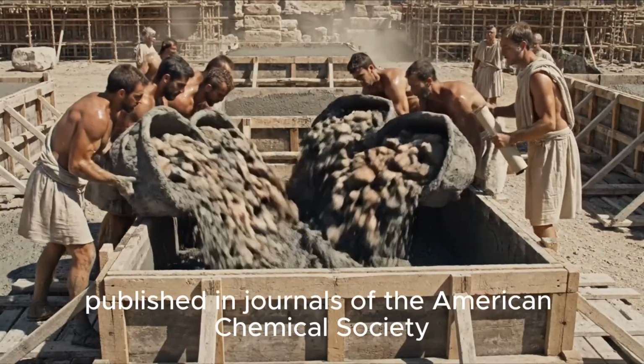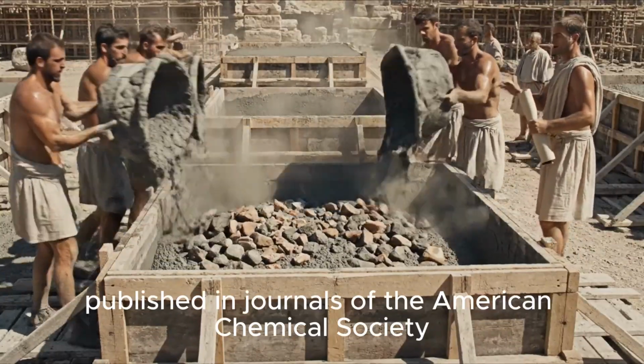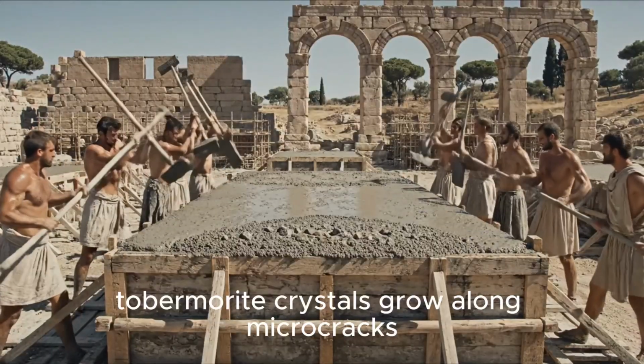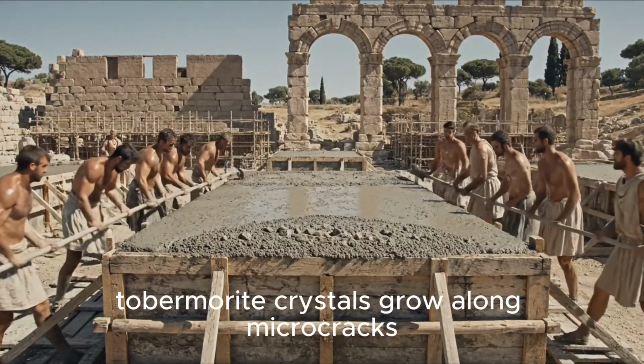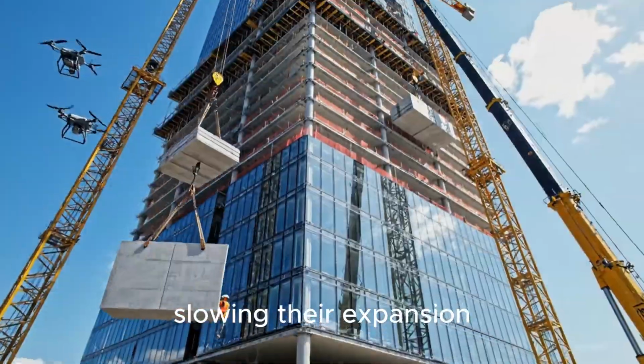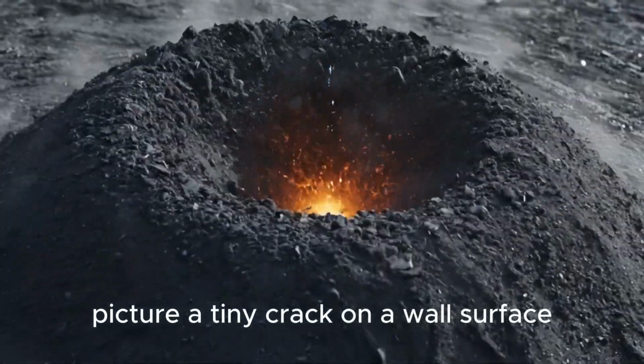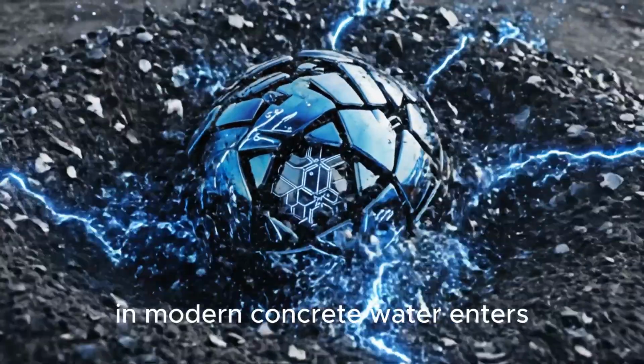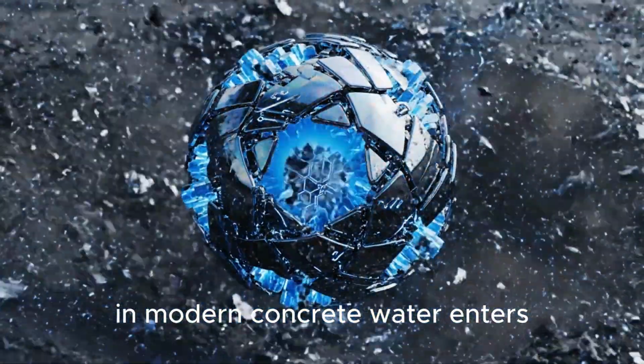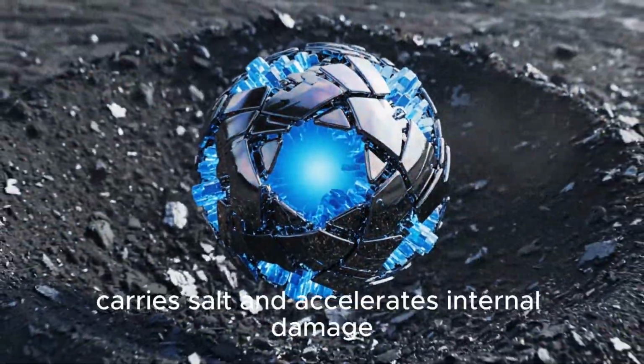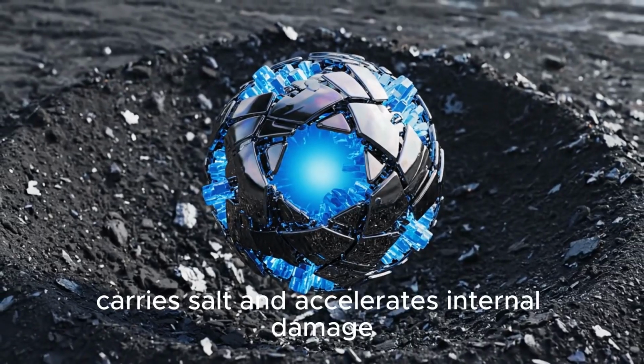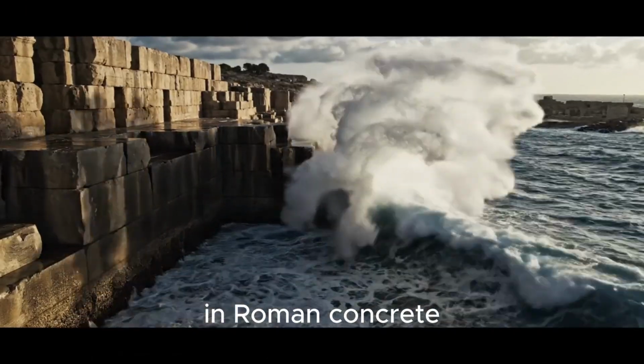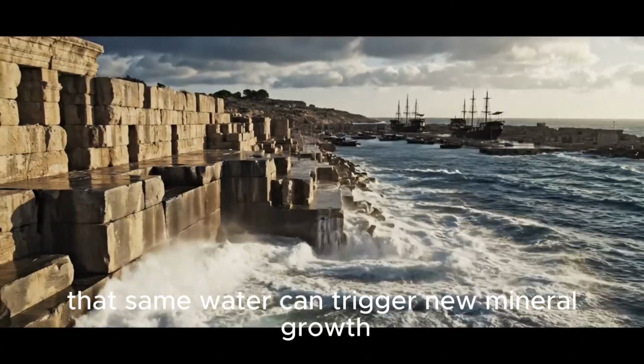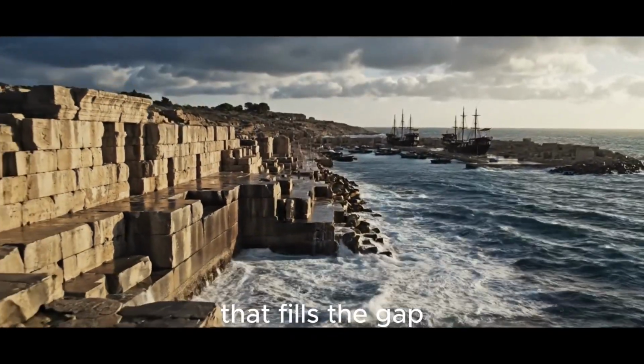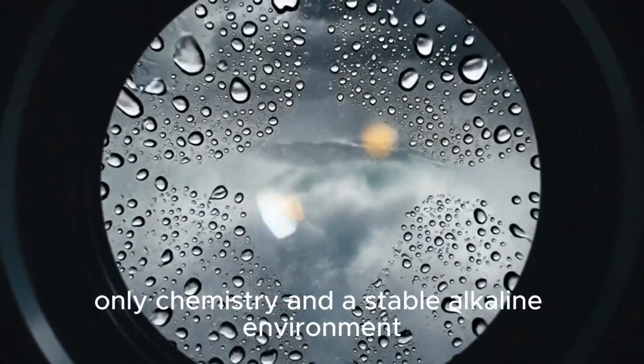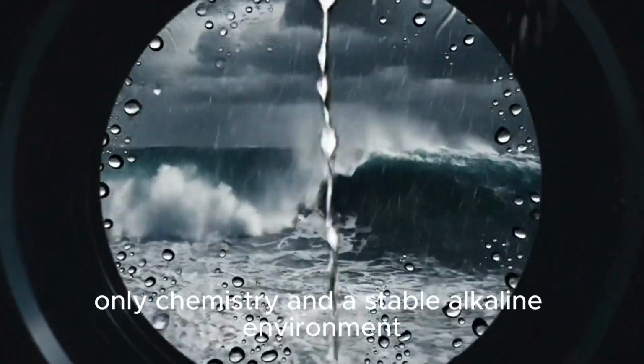Research published in journals of the American Chemical Society has shown that aluminum tobermorite crystals grow along microcracks, slowing their expansion. Picture a tiny crack on a wall surface. In modern concrete, water enters, carries salt, and accelerates internal damage. In Roman concrete, that same water can trigger new mineral growth that fills the gap. There's no magic involved, only chemistry and a stable alkaline environment.